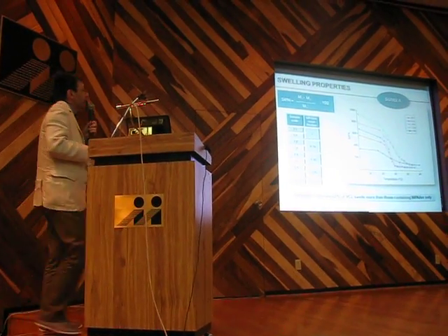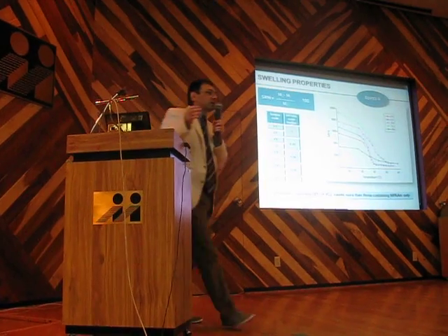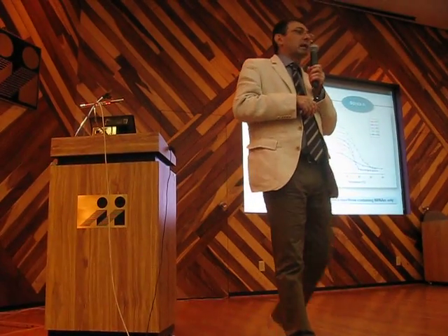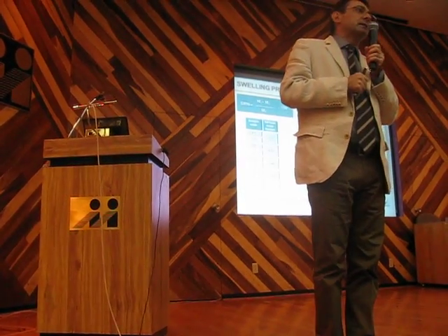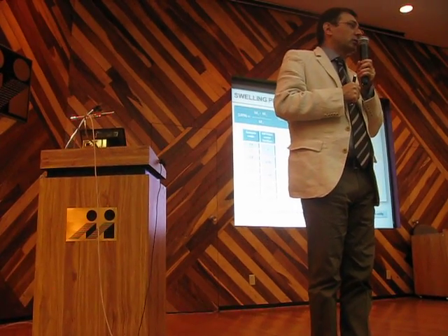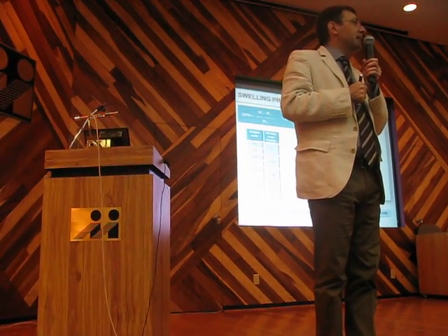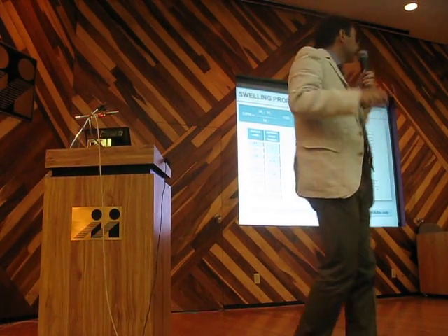So we can substitute at least 25% of NIPAM with vinyl caprolactam. The system is less cytotoxic, it's cheaper, and the swelling is higher.